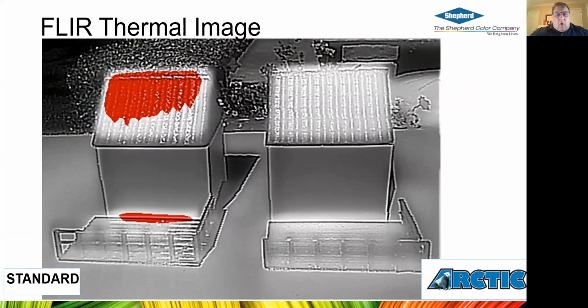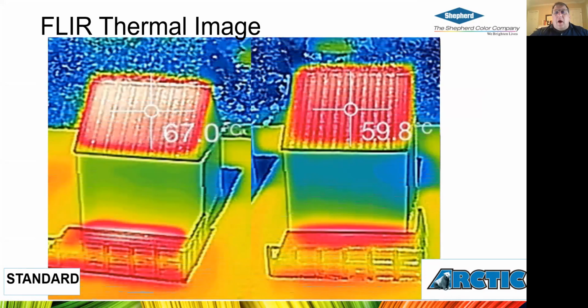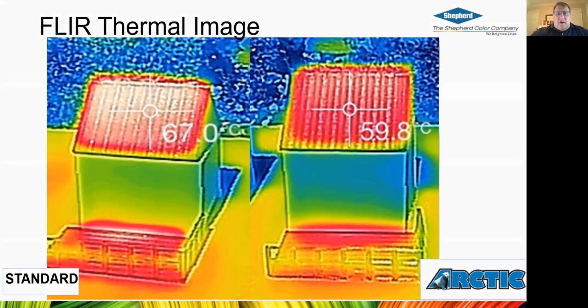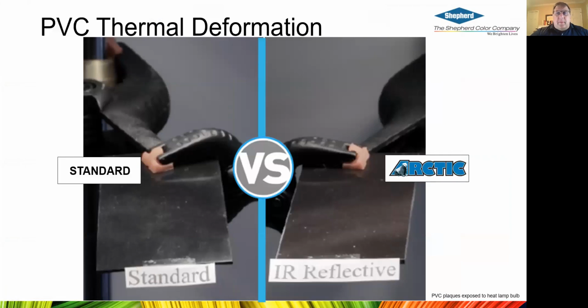And we can look at this qualitatively. We can also look at it quantitatively. So the standard pigmented roof actually has a surface temperature of around 67 degrees Celsius. Meanwhile, the Arctic pigmented roof of the same color is 7 degrees Celsius cooler than the standard pigmented roof. This is what the Arctic technology does: for the same color, you can have a lower temperature when you're exposed to the sun. And this is useful in a number of applications.